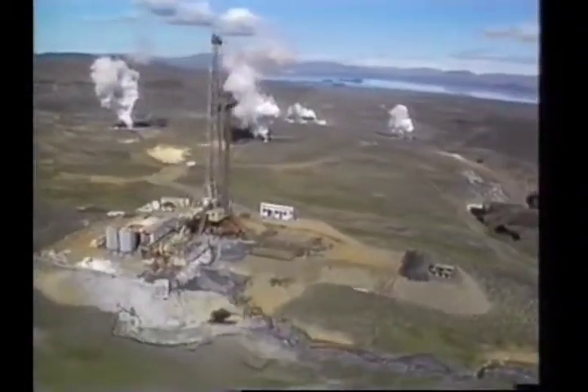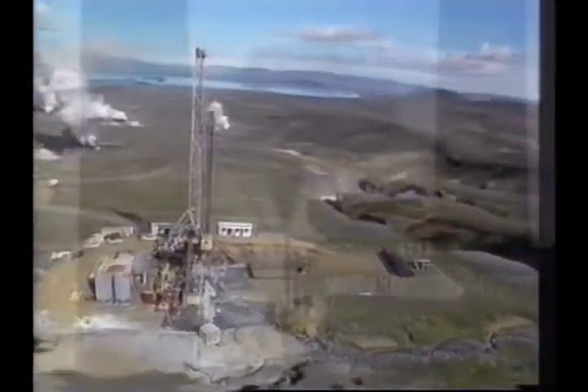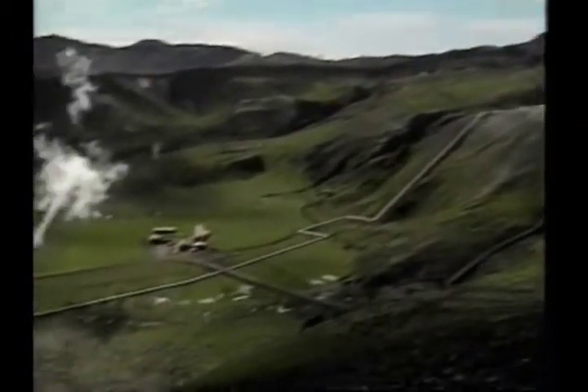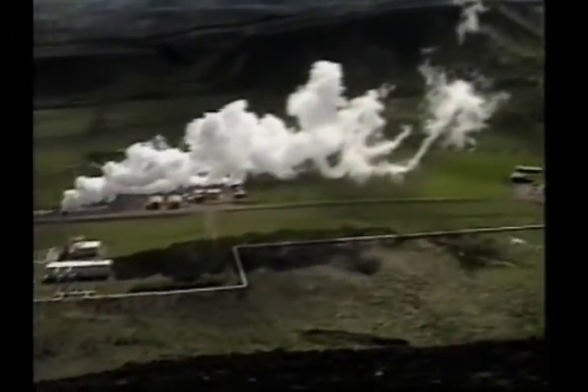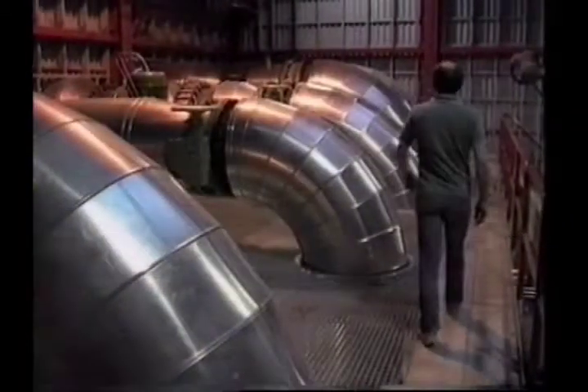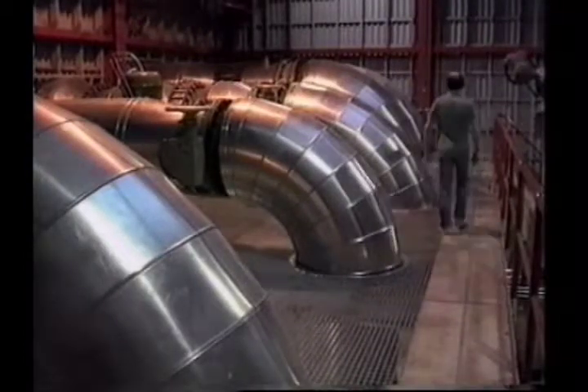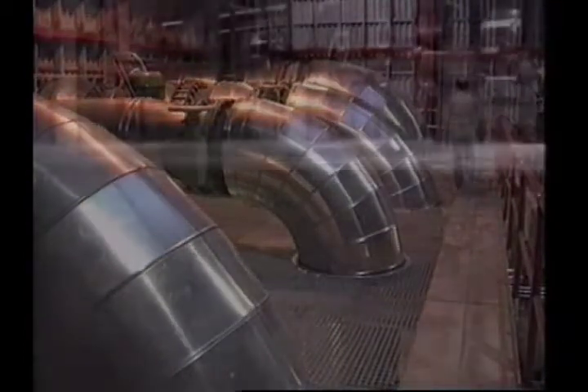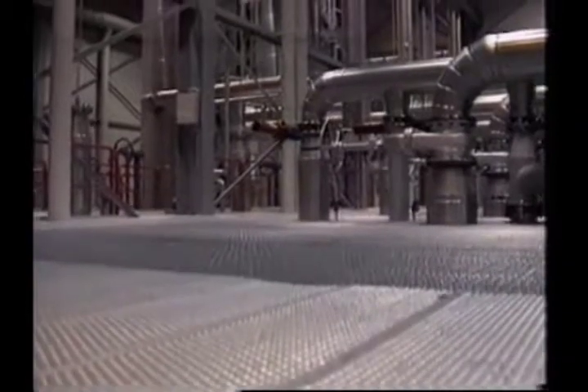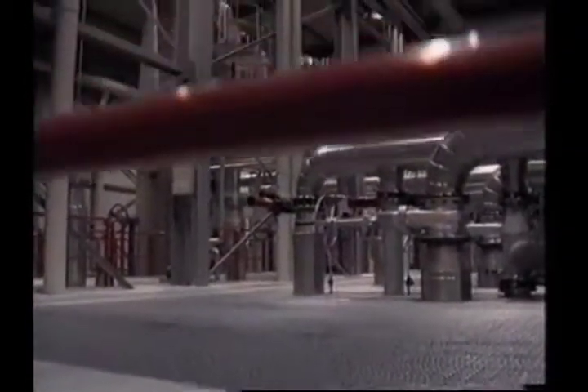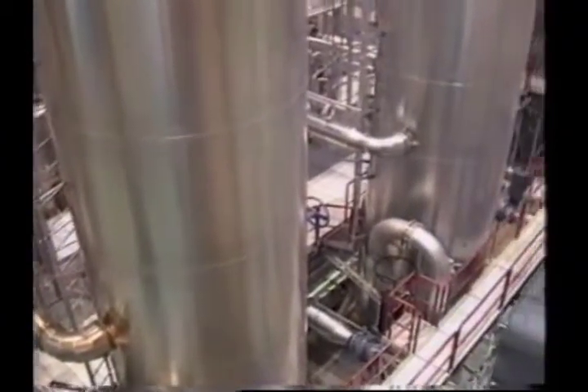Power generation throughout the world relies in most instances on the use of steam, both natural and processed. At this geothermal plant, highly corrosive sulfur-laden steam causes severe deterioration of the low-pressure turbine casing, resulting in severe pitting and loss of wall thickness. Belzona 1591, with its high temperature resistance, is capable of restoring the integrity of these units while protecting against further erosion-corrosion attack.